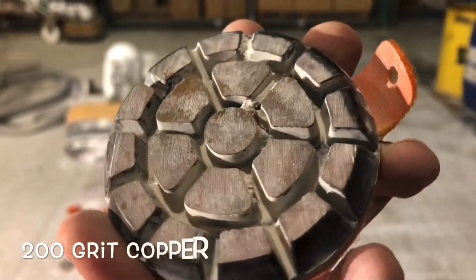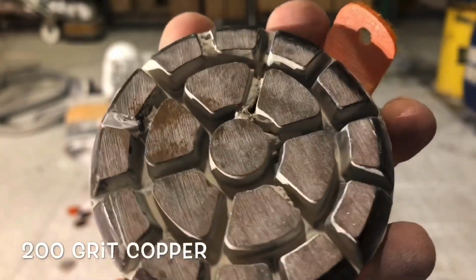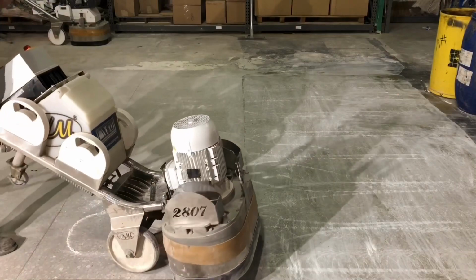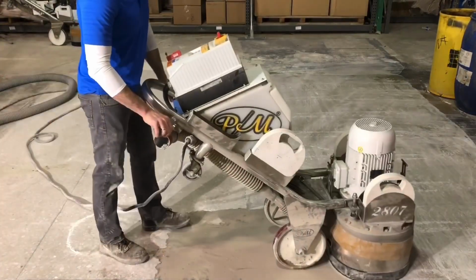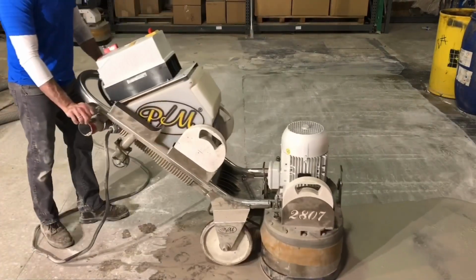Once the epoxy was given sufficient time to cure, it was then removed using a 200 grit copper pad. The goal with the 200 grit copper pad is to only remove the overfill of the epoxy. We do the step wet so that the friction caused by the diamonds when run dry wouldn't help to rip that epoxy back out of the holes. So again, the only goal of the 200 grit copper is to remove that overfill, and then once that's complete, it also is going to remove the scratches from the 70 grit step.